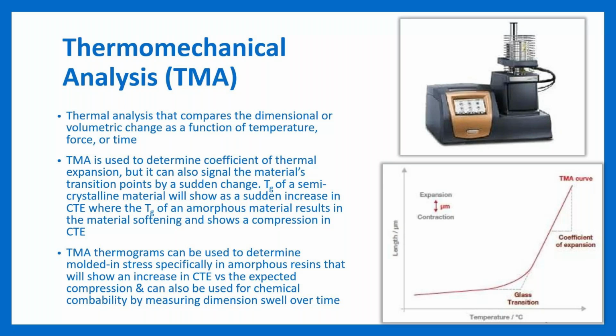And so if you look here on the graph, you can see it's kind of gradually there, and then it kind of takes a steeper turn. This is going to be your glass transition temperature of a semi-crystalline material. And then your TG of an amorphous material, because it's more of a gradual softening, as you'll hear us describe it quite often. Generally what happens with your amorphous material, because it gradually softens, it'll actually show a little bit of a compression in your CTE. So you'll see a little bit of a drop. So this particular curve is not for amorphous, it's for semi-crystalline. So we can use that to determine those thermal transition points as well.